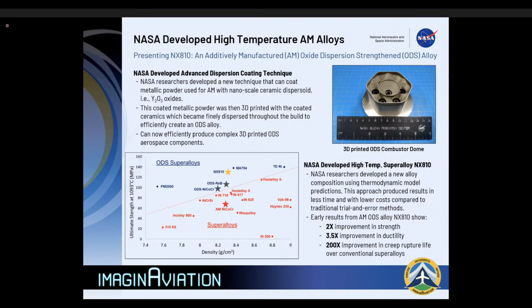And so that was really encouraging for us in terms of looking for an alloy that we can use for really extreme temperatures that you're going to thermally cycle. And lastly, the temperature difference between its solidus and liquidus temperature, the range where it fully melts or fully becomes solid, is a very narrow temperature range. And what we're finding is that if that range is narrow, it appears to be a more printable alloy for additive manufacturing. You're less likely to form segregation, cracking issues, and high residual stress.